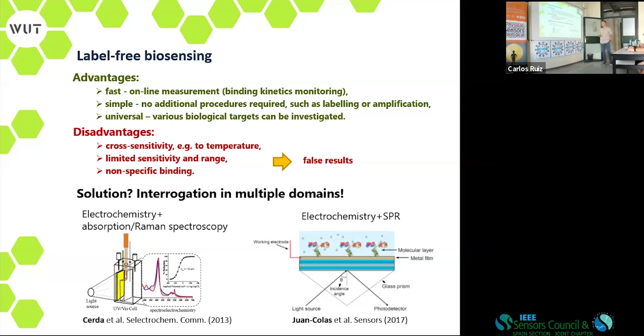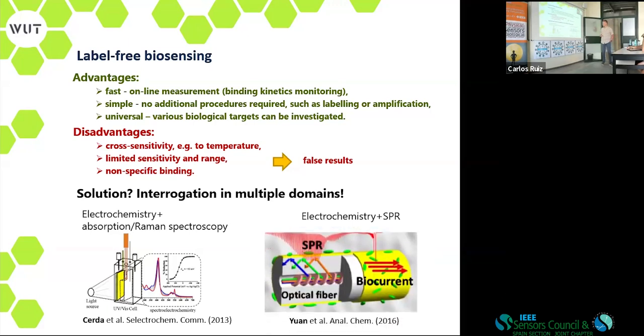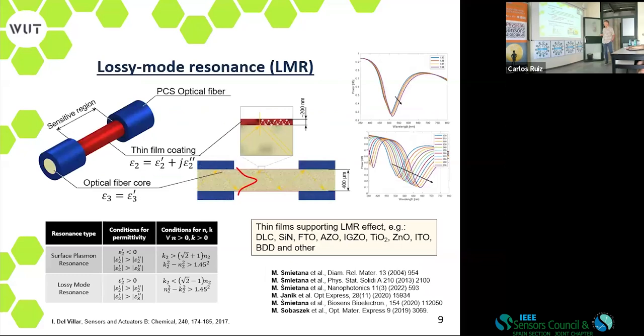One of them is to interrogate these sensors within different domains. So interrogate the same sensor at the same time using some other means, like electrochemistry, in this case this is an electrochemical setup, or electrochemistry plus SPR. These sensors have been reported. One of them was reported on a fiber, but it's quite a complex structure. You may see that there's a gradient in the core, it requires fiber processing, and then gold must be deposited. So quite a complex structure, sensitive, but still complex, and in terms of mass manufacturing, it's not suitable. So that's why, from the perspective of mass manufacturing, as biosensing, we focus more on simpler devices.